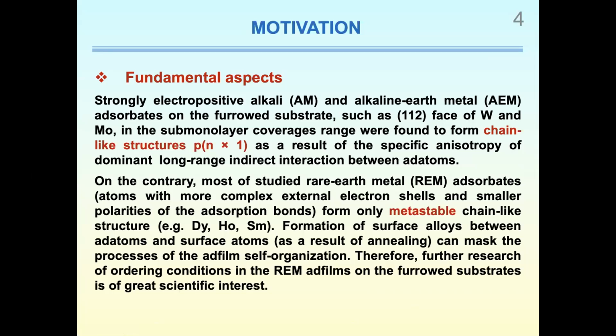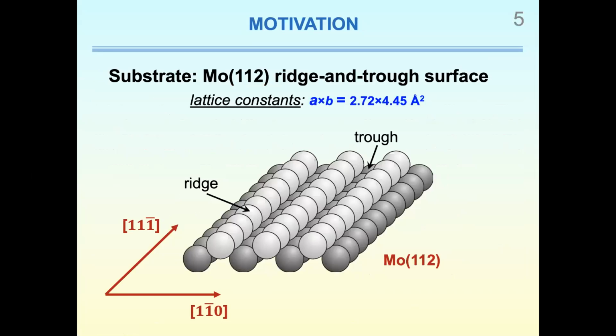In the present work, we studied the atomic structure and the work function changes in the process of cerium submonolayer growth on the molybdenum 112 surface. The molybdenum 112 face, which was used in our study as a substrate, is an extended surface which consists of furrows alternated by ridges. The high anisotropy of this surface, as well as molybdenum's refractory properties, made it highly attractive as a sample for surface science studies.